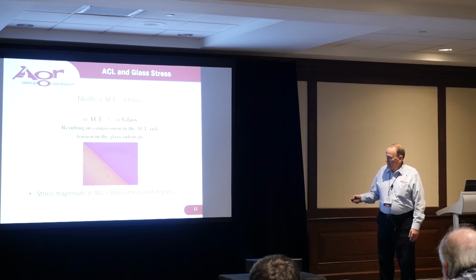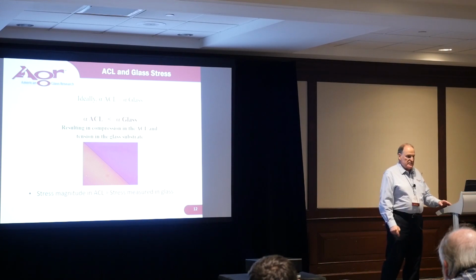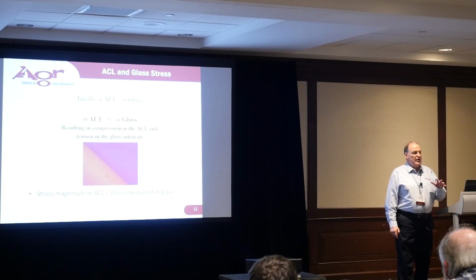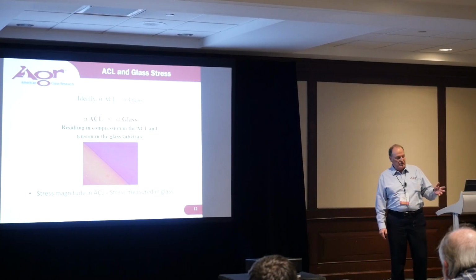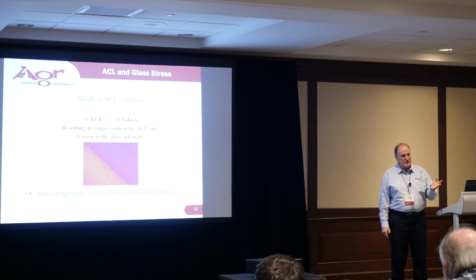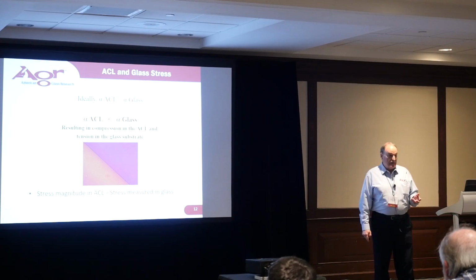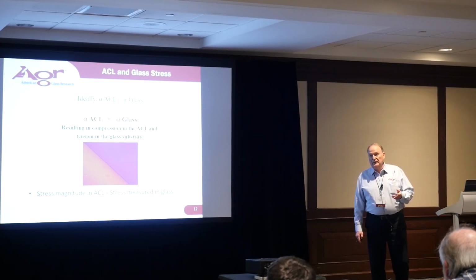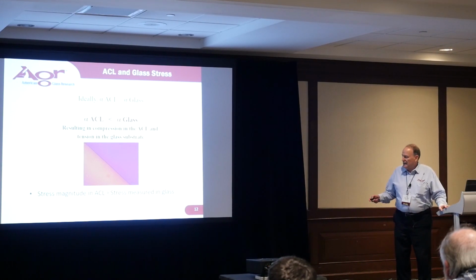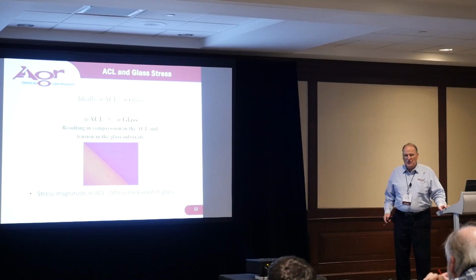Down here at the bottom of this slide, we'll talk about this first. In the past, what we have done is we simply make the assumption that the stress in the ceramic label is going to be approximately equal to the stress that we can measure in the glass. Opposite in signs, of course, but approximately the same magnitude. Now, knowing that the ceramic label is thin, and it's a solid layer, we have to modify this assumption slightly by saying, yes, the magnitude may be similar, but most likely a little bit higher. How much higher?